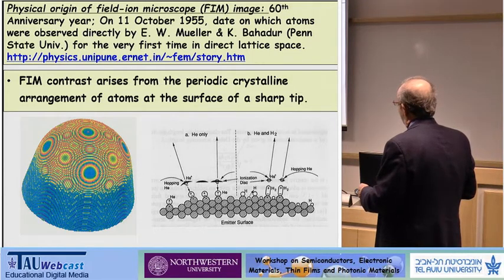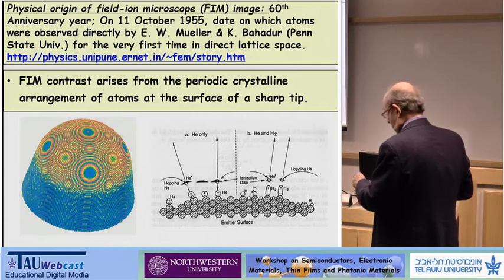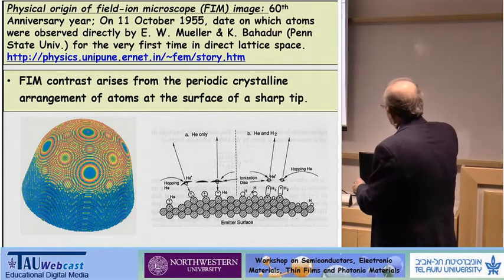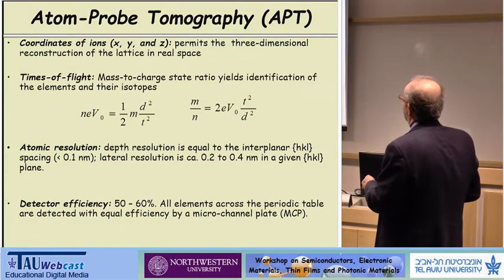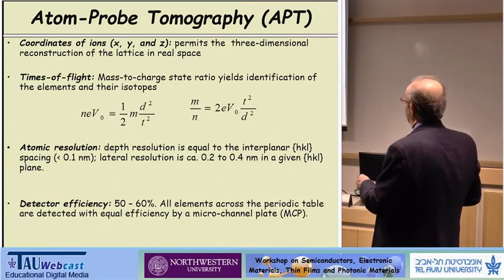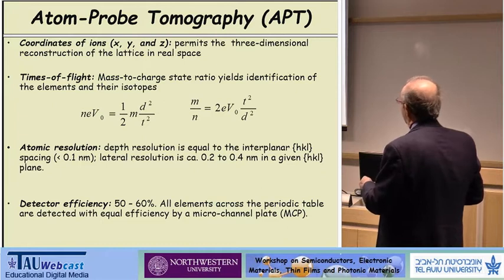And then they're ionized a few angstroms above the surface. So each atom has a cone of helium atoms that give you a signal, and you can see the atoms in real space. And forget about the right-hand side with hydrogen. So the key points of the atom probe: you determine the positions X, Y, and Z in real space. And from conservation of energy, you can determine the mass-to-charge state ratio.